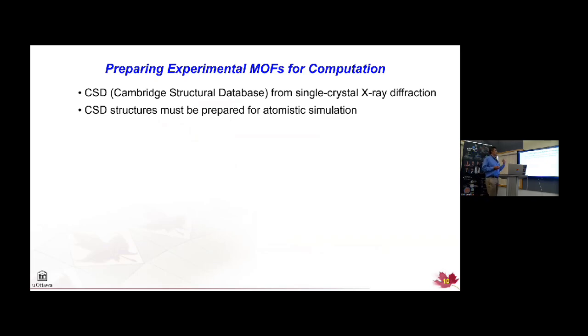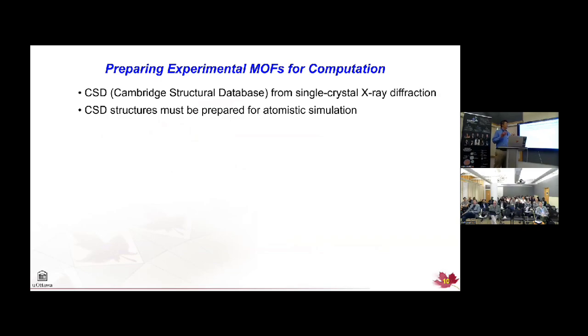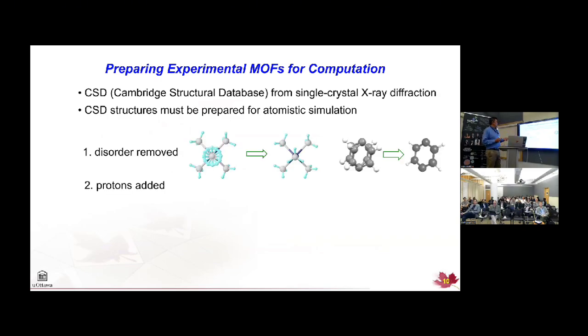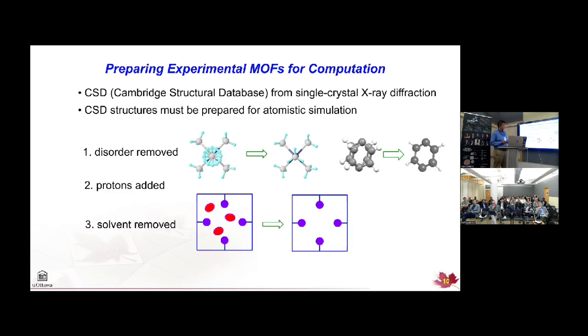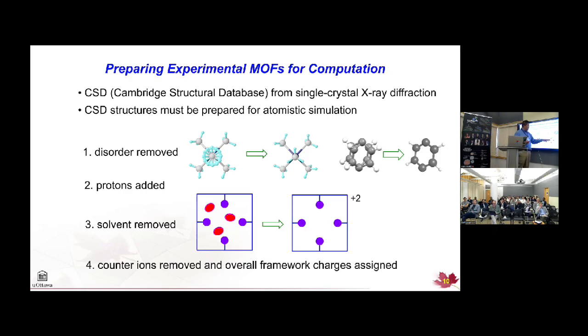Well, all of these structures come from the CSD, and these are single crystal X-ray diffraction structures. When you get the results from those experiments, you can have disorder, where you have a few low energy conformations that are diffracting. So you have to clean those up. The method doesn't pick up on the protons, so you have to add protons. And when the MOF crystallizes, it usually crystallizes with some co-crystallants or solvent, and you have to remove that to make the material porous. They do that experimentally by activating it. And lastly, the framework itself can have a charge. So if you remove the counter ion, you have to label the framework as charged. Otherwise, your computation will not be particularly accurate.